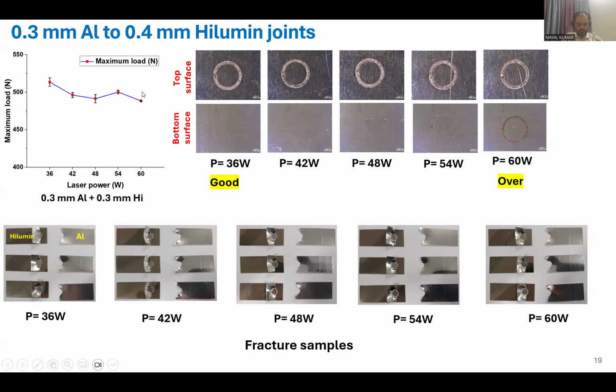As I mentioned, a similar examination has been done for the 0.4 as a bottom sheet, and the top sheet is the same here, same dimension, everything same, same laser. Only there is a change in power because the bottom sheet is 0.4 millimeter. So there is a slight increase in the laser power because the bottom sheet is capturing more heat and dissipating more heat as it is quite thick.